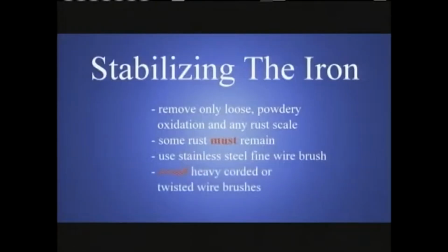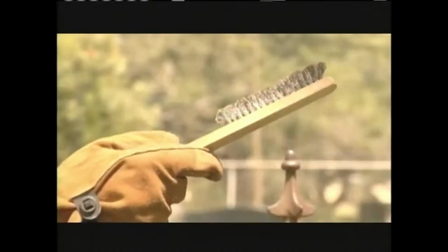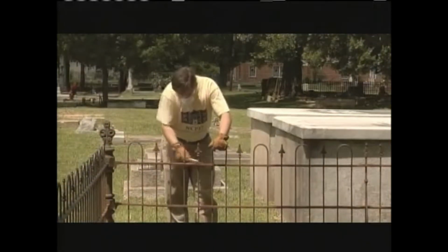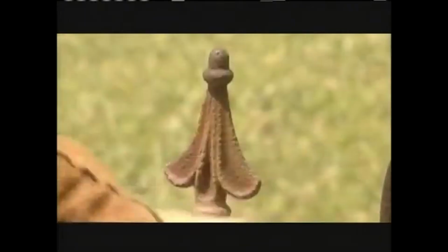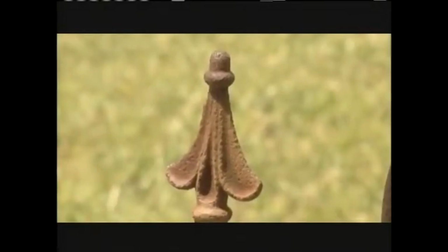Heavily corded or twisted wire brushes are too aggressive for historic ironwork and can easily remove too much material. When selecting a wire brush, you want to choose a finer wire. The fine wire lasts longer and is more flexible to reach tough spots and corners. I do not recommend sandblasting, since some of the fence's detail could be lost and the iron will get overcleaned.